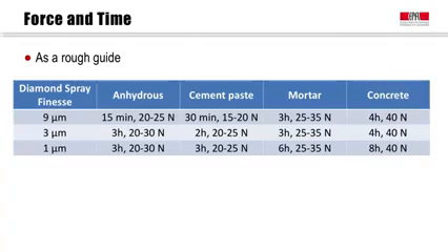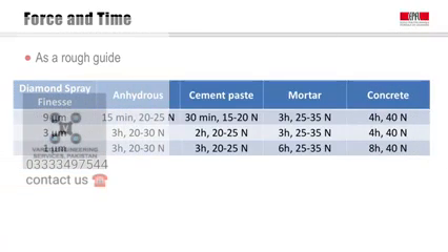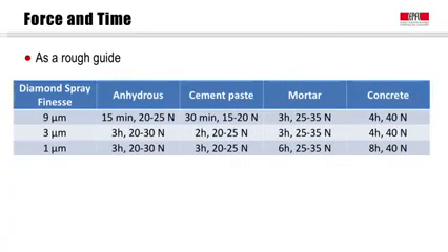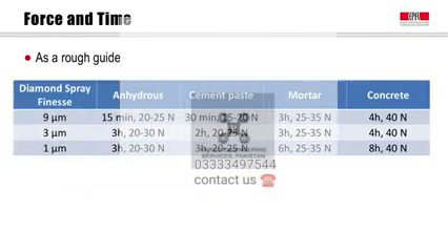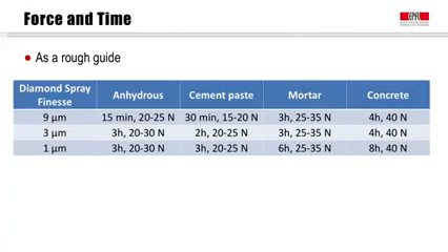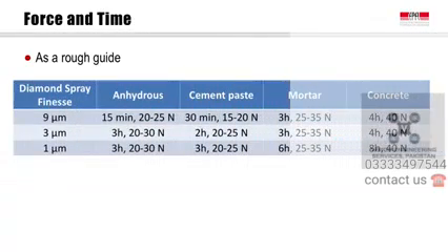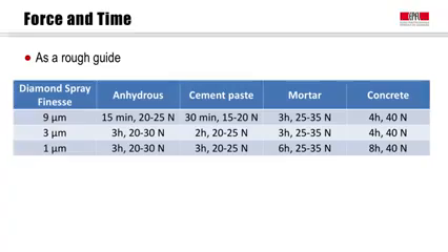Then the polishing is carried out using a spray containing diamond particles and a lubricant, petroleum. There are at least 3 steps corresponding to a diamond particle size. We always start with the biggest one, 9 microns, and finish with the finest one, 1 micron. In this slide, I show you some indicative times for each step depending on the sample type: mortar, paste, concrete. Of course, this time must be adapted to your samples and sample age.